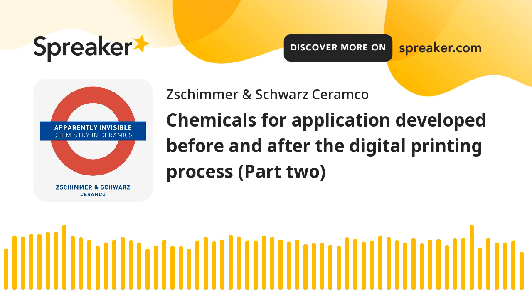However, it's important at the same time to avoid that raw tiles arrive under the print heads with a too high temperature. This, in fact, could overheat the printing bar, leading to many problems, such as, for example, a partial or a full obstruction of the nozzles, because, of course, of the thermal shock, we could say.